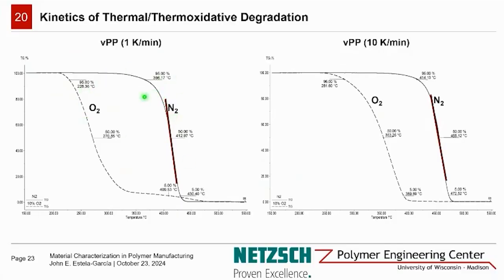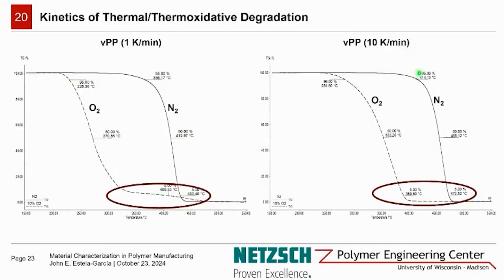For the inert environment, we're observing a single slope, which is characteristic of polypropylene and other polyolefins during pyrolysis, and simply details chain scission. When we observe the oxidative environment curves at the slower heating rate, there's a secondary slope. That means that there's a different reaction occurring, but we can't really appreciate that at the higher speed; the second slope is not readily apparent. So this indicates that this is a slow reaction that can't be observed at higher heating rates. So this is now detailing the importance of adequate standardization of testing procedures.